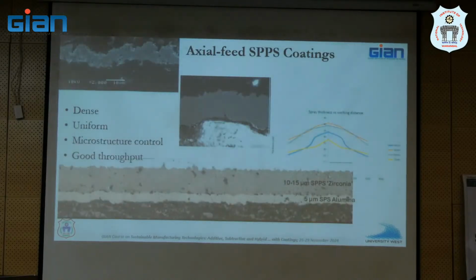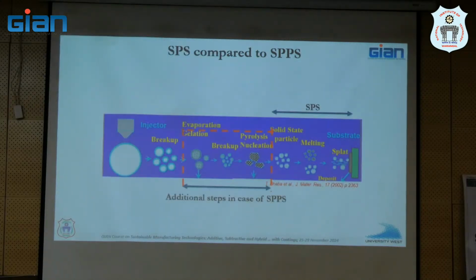So that was the beginning, and now we have used the same thing which we had learned from radial feeding and extended it to axial feeding. So we are able to get very dense SPPS coatings, and I want to make this point clear. If you use a suspension, all these additional steps are not necessary. If you use a solution precursor, you have these additional steps before powder is formed, and then the rest of the process is the same. Is that clear? A little bit? Yeah.